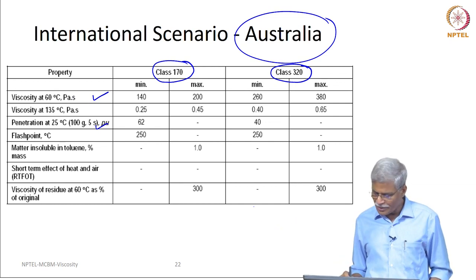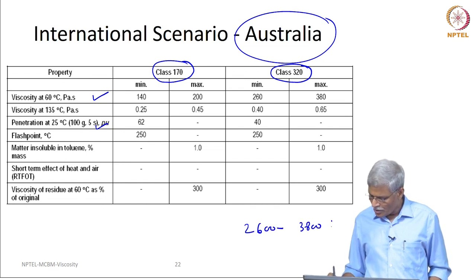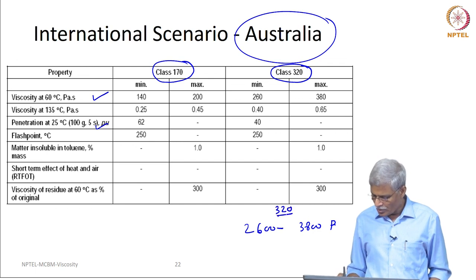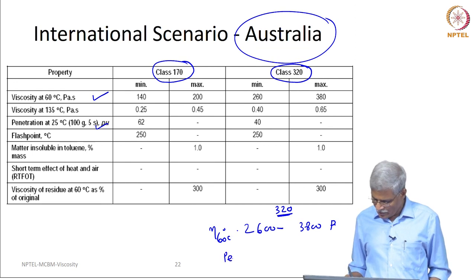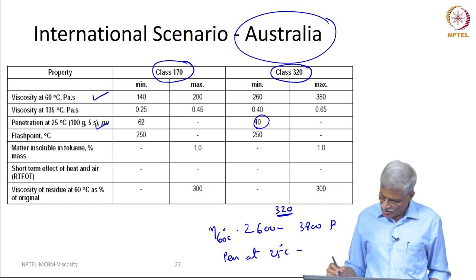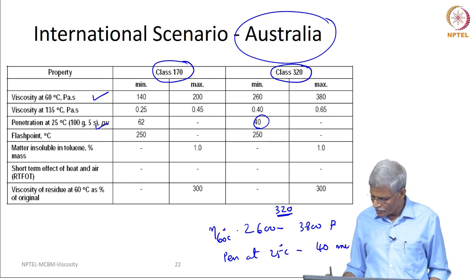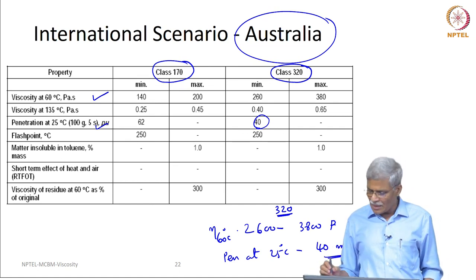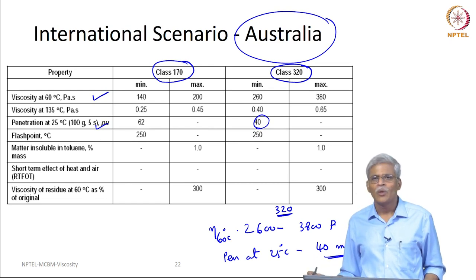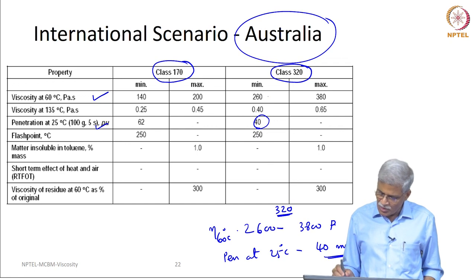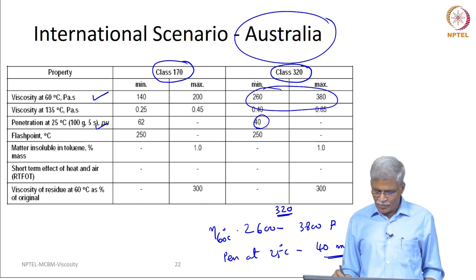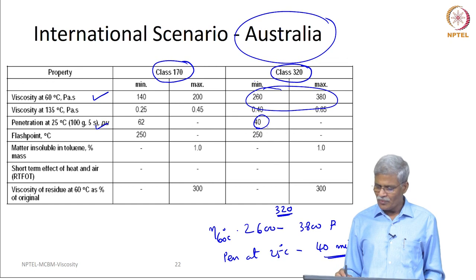For your convenience, if you want to write it in poise, this is going to be 2600 to 3800 poise for Class 320. So this is the viscosity at 60 degree centigrade and the pen at 25 degree centigrade is taken as a minimum of 40. This is a classical viscosity-based specification because the viscosity values are bounded — there is a minimum value, there is a maximum value — whereas the penetration value is left with a minimum.